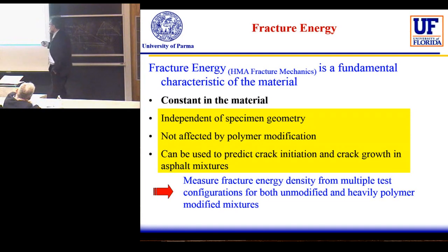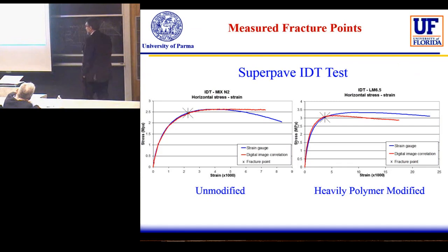Again, we did the test in different configurations for both kinds of bitumen, and here I will show you some of the results. Again, double way: the strain gauge in the back and DIC in the front. We found quite a nice correlation, although the first crack of course was not in exact agreement, because we are looking at both sides and it is not a three-dimensional analysis, and something that can happen in one face is not exactly at the same time in the other. But considering that the thickness of the specimen is 5 centimeters, it's possible to assume that the time difference does not make a big change. So what's happening in one face closely follows what's happening in the other one.